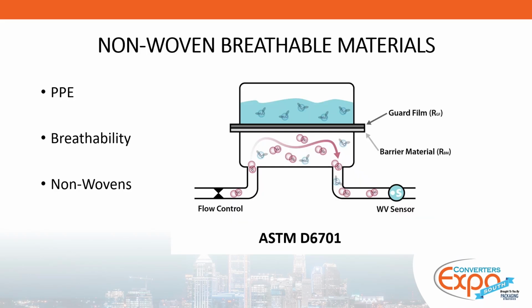So historically, the cup method, known as ASTM standard E96, was used for very high transmitting water vapor materials. But there is something specific with that method, whether you're using a wet cup or a dry cup, that once you get to a certain transmission rate level, a lot of questions arise. Questions like, if so much moisture is going through my material, how can I be sure that I'm really challenging one side with 100% relative humidity?